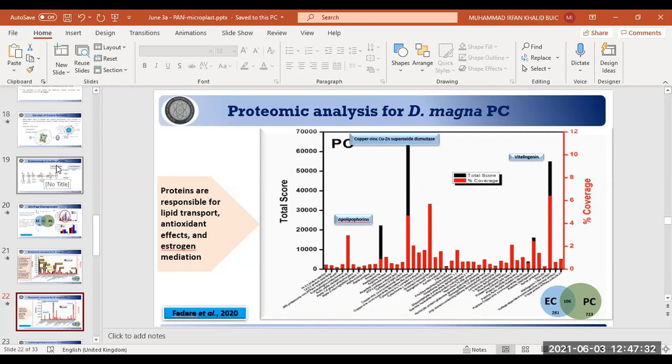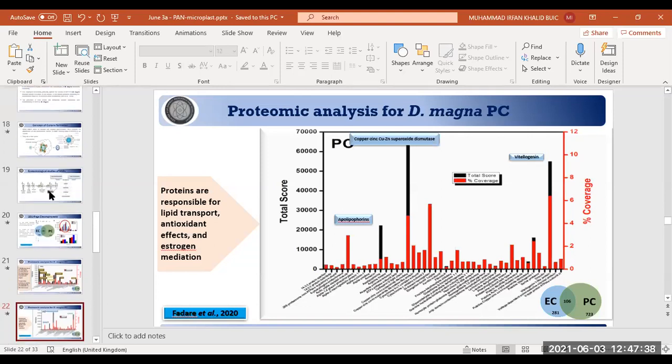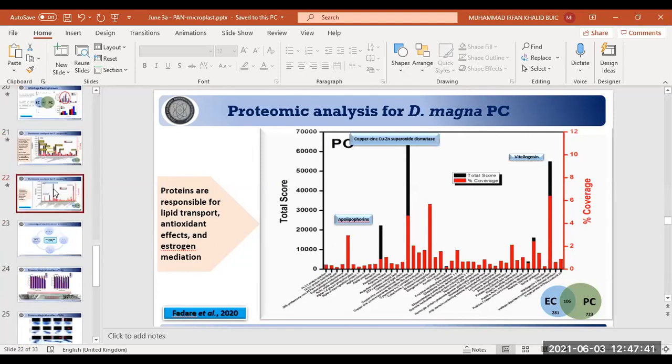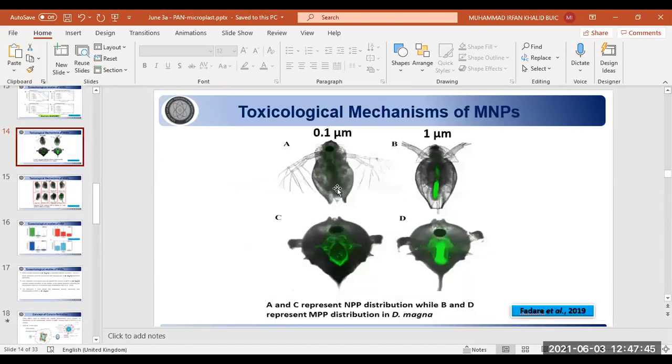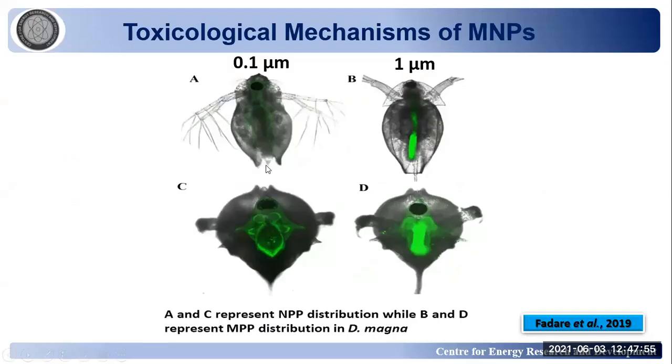Yeah, I think you are right. What is important is what type of toxicity takes place, and that's why we use bioimaging to understand. What we can establish presently is that the immobility or mortality in Daphnia magna when it comes to nanoplastics is a result of physical toxicity. Because the ones that consumed the 1 micron particles actually expel them, and they are fine.